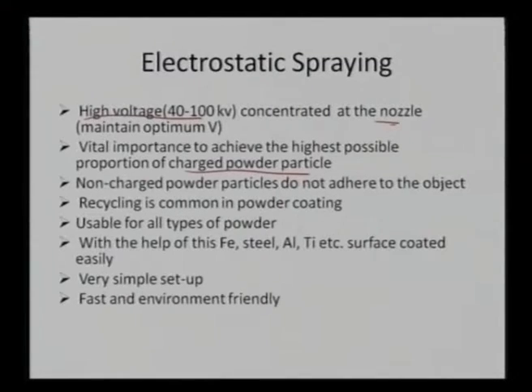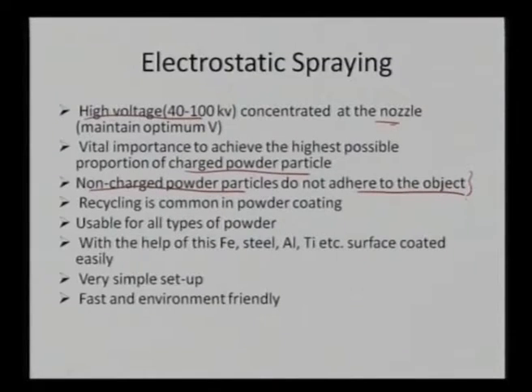After that, non-charged powder particles do not adhere to the object because they can dissipate the charge very easily. So, in this case, we need powder particles which can get charged, and that charge is created by the voltage which is concentrated at the nozzle. Once we can do that, we can let the powder adhere to a particular substrate, and the powder which is going outside, which is not sitting on the substrate while the process is going on, that extra powder can be recycled back to the powder hopper, and from there we can circulate the powder again. What is the overall working and functionality of this electrostatic spraying?